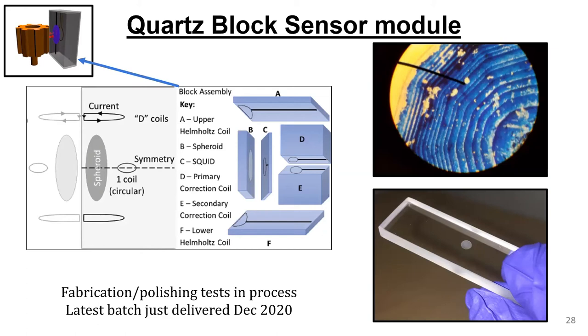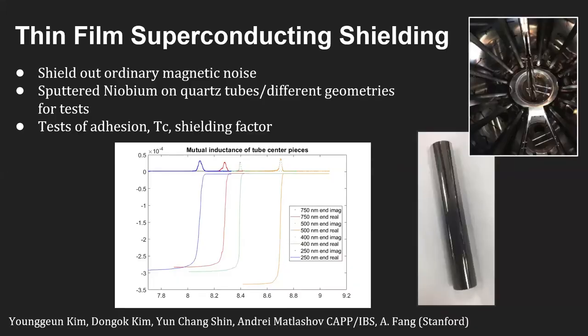So this entire assembly, of course, needs to be protected from external magnetic fields by a superconducting boundary. And so the way we're going to do that is to deposit thin film superconductor over the surface of that quartz block. The folks out there have been helping us measure superconducting thin film shielding using a sputtering system with niobium. Some initial tests that we've been doing have been sputtering niobium not on our final quartz block, but rather on other geometries, including tubes, just to evaluate the quality of the superconducting films prior to coating the real final sample chamber.